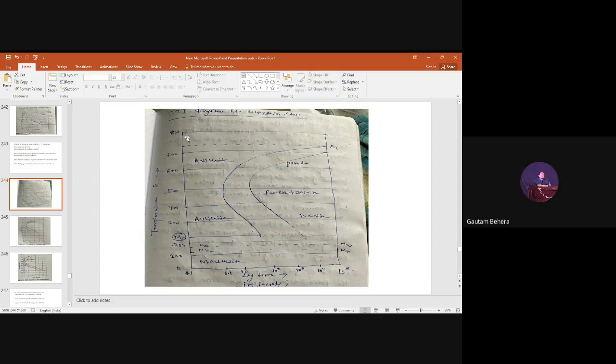See, suppose you get a big piece of steel. The first thing you have to do is cut it into smaller pieces, because you want to do isothermal transformation. Isothermal transformation means you have to do transformation at a constant temperature. So you have to choose at what temperatures you want to do transformation.